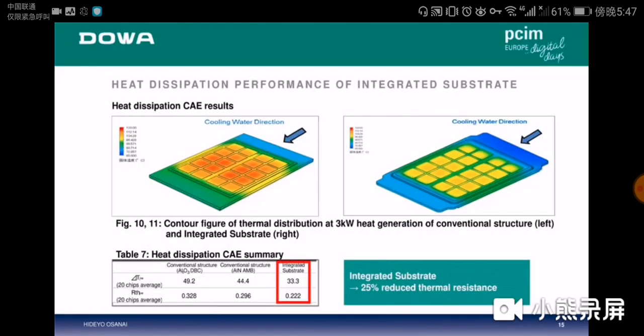Figures 10 and 11 show the temperature profile when the conventional structure and the integrated substrate generate 3 kW of heat. When using the integrated substrate, delta T and thermal resistance from chip to cooling water decreased by about 25%. This result was realized by eliminating the system soldering and TIM.